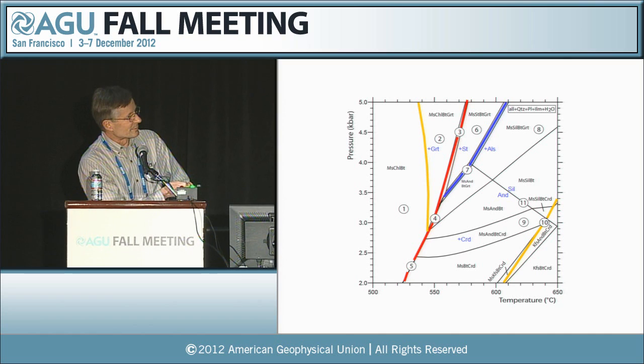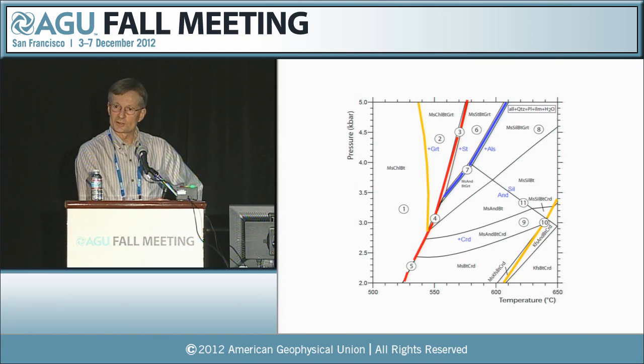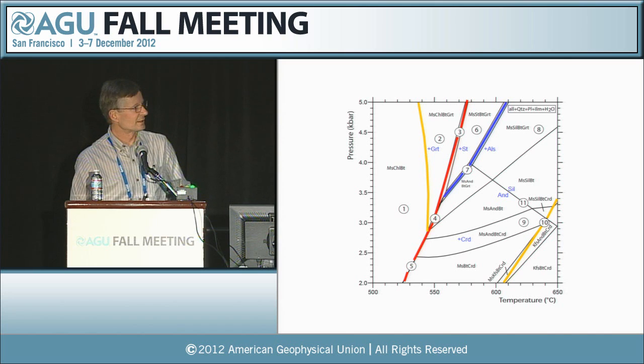This green one here is the muscovite quartz breakdown. This is the chlorite to garnet reaction, which is not quite as highly entropic as these ones, or at least the unit entropy change isn't as big because it occurs over a much bigger divariant interval due to iron-magnesium exchange.